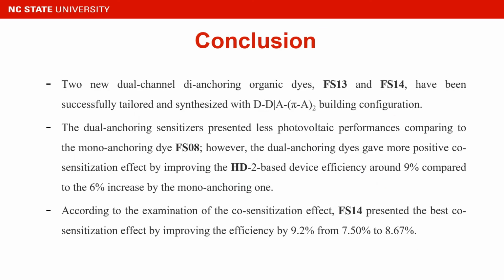In conclusion of this paper, the two new dual channel anchoring organic dyes FS13 and FS14 have been successfully tailored and synthesized with the D-(D-A-π-A)2 building configuration. The dual anchoring sensitizers present less photovoltaic performance compared to the mono anchoring dye FS8. However, the dual anchoring dyes gave a more positive co-sensitization effect, improving the HD-2-based device efficiency by around 9% compared to a 6% increase by the mono anchoring one.